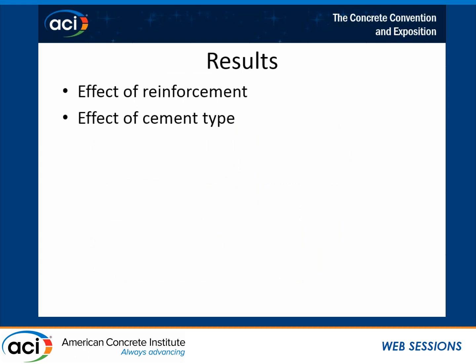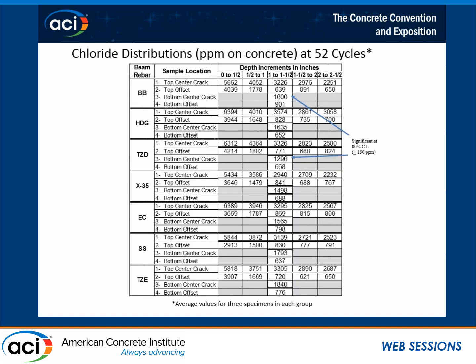So for the results, we'll look at the effect of what different types of reinforcement had, then we'll look at the effect of cement type. This is a little complicated slide, but basically what we did is we looked at the top center of the crack at various depths. Then we looked at the offset away from the crack, and the first thing you can see on all of these is that at the surface they're not too much different. A little bit more there, but as you go down, you can see the effect of the crack.